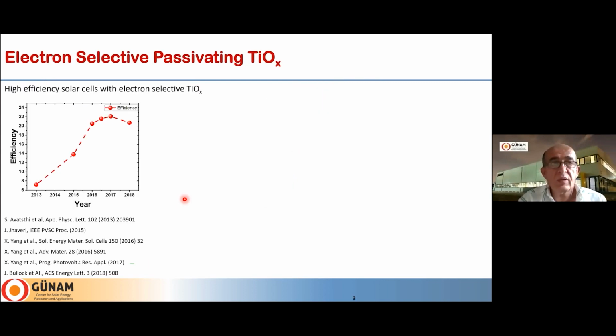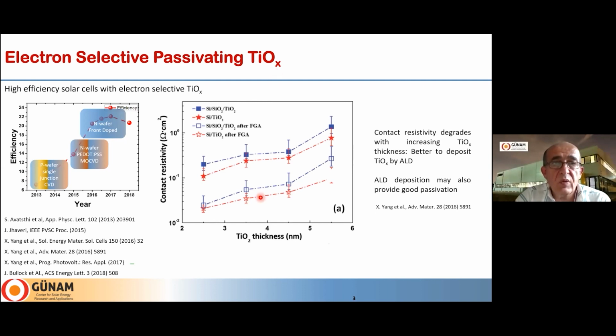Okay, I can go to the next topic, which is the electron selective passivating titanium dioxide or titanium oxide. Up to now, I have been talking only about the hole selective layer. Now, the next few slides are about the electron selective layer, which is titanium oxide. There have been many studies in the literature. You can see the list here. They have fabricated even solar cells with high efficiencies. In general, the contact resistivity with titanium oxide gets higher with increased titanium dioxide thickness. This is maybe expected. So you need to have good control over the thickness, because the contact resistivity is extremely important, especially for the fill factor of the solar cell.